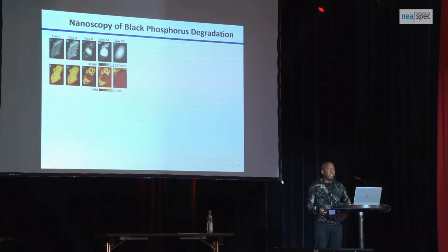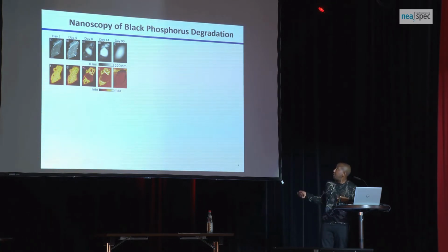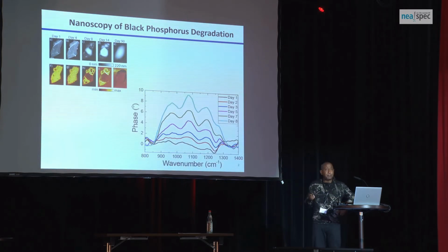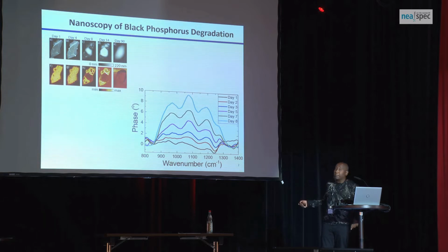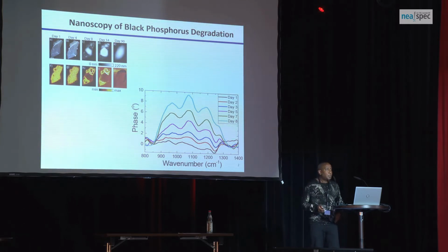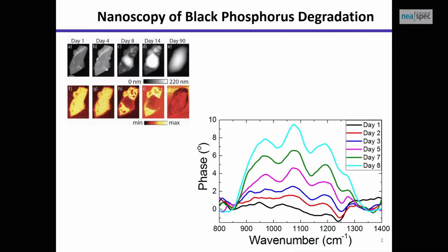If you sit in one of these bubbles that you see here in the image, if you sit at one of these points and take spectra, you see something like this. In the beginning the spectrum is sort of flat, and then as time goes on it starts to have structure, and eventually you get something like this. So this is really quite exciting, right? You can observe, really in front of you, bonds making and breaking. That is what you're looking at.